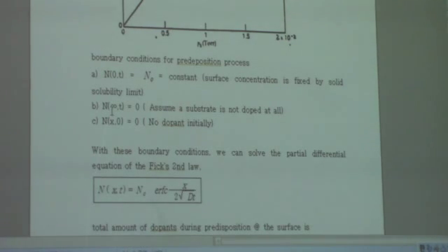And if we assume an infinitely long depth of the single crystal silicon, the 600 micron thickness, we can assume that it is infinite, because we're going to diffuse at most 1 or 2 microns. Typically 1,000 angstrom at the junction depth, so compared to that, the 600 micron, we can assume infinity.